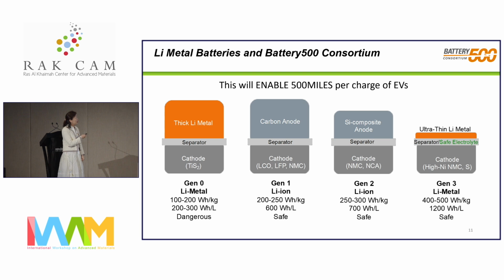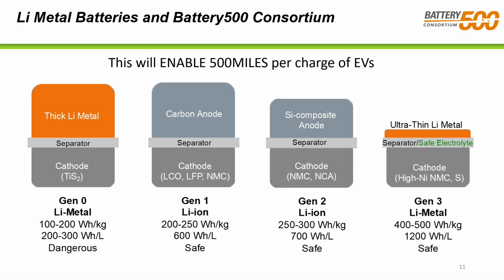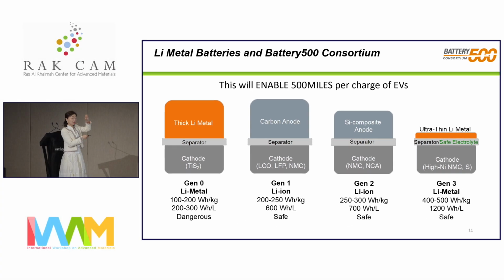So he used a very thick block of lithium metal and the titanium disulfide as the cathode. You were saying, oh, why didn't he use lithium cobalt oxide? Lithium cobalt oxide did not get invented until Professor Goodenough read Professor Whittingham's paper in 1976, right? So he didn't have a choice, and all these very thick, millimeter-thick lithium metal, once it's being cycled, becomes pulverized and becomes very high surface area lithium, and that's where all the safety problems happen.